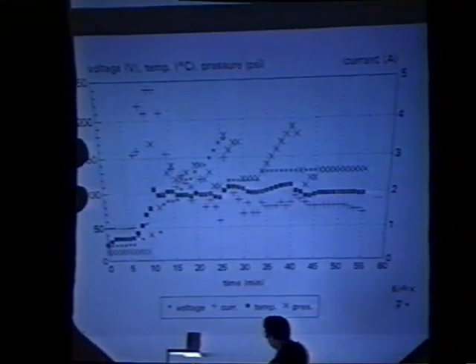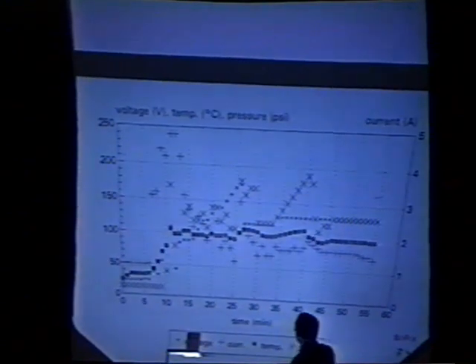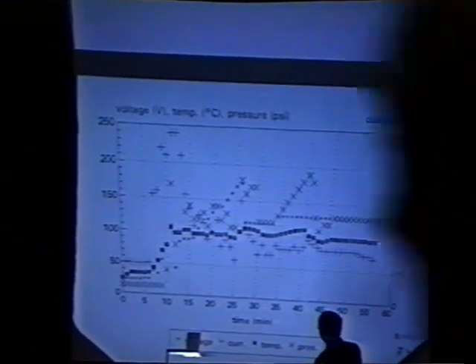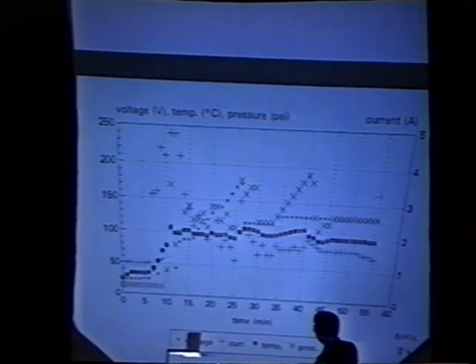Number 4 was the compromise experiment for this procedure. So the temperature increased to 120 degrees. The pressure increased, but in a controllable way. The current peaked at about 5 ampere and typically 2 ampere.